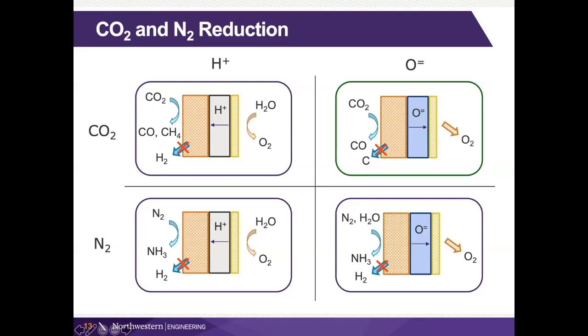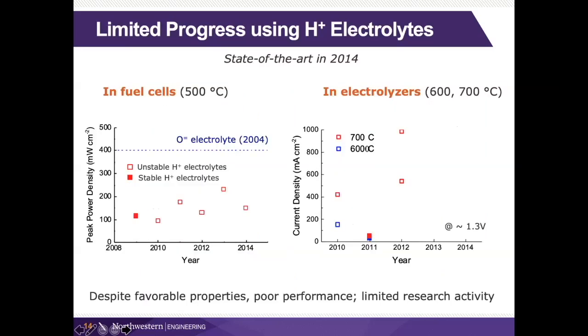And in the case of making ammonia, the proton conducting system has, in my view, really a big advantage over the oxygen ion conducting system. You also would not want to go very high temperature in this case. The temperature question was raised. You'd not want to go to high temperature because nitrogen and hydrogen thermodynamically will dissociate. So thermodynamics are in your favor at lower temperature. You just need high enough temperature in order to catalyze the reaction, get over those reaction barriers.